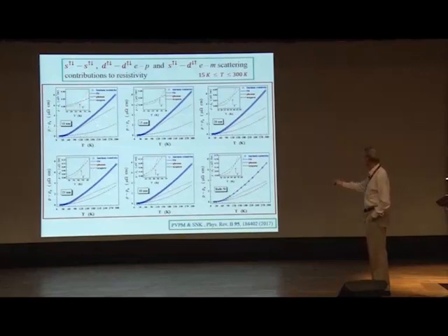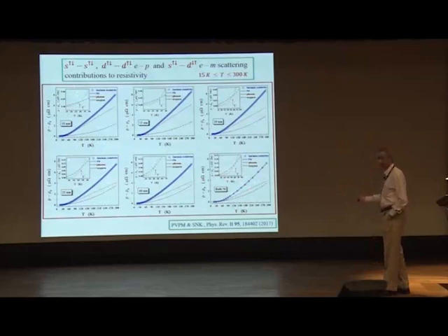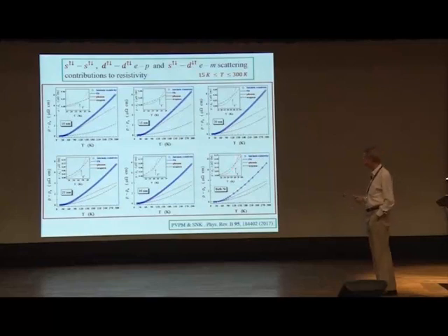That crossover temperature shifts to higher temperatures as you increase the size. For example, here it was about 30 Kelvin. For bulk nickel, it's around 60. So it gives you an idea of how different scattering mechanisms become important in different temperature ranges, and you can even know their actual magnitude.